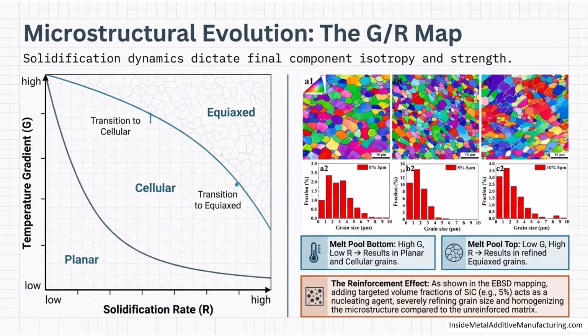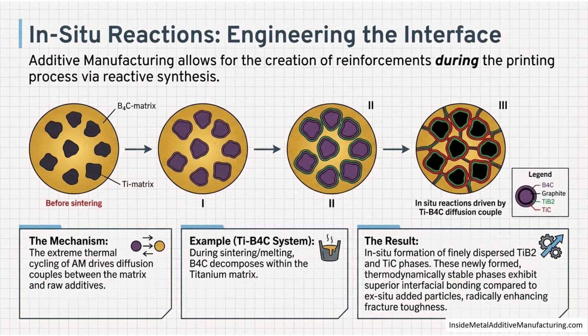Notice the reinforcement effect in the EBSD mapping. Adding targeted volume fractions of silicon carbide acts as a nucleating agent, severely refining grain size and creating a more homogeneous, equiaxed microstructure compared to unreinforced alloys. Instead of just adding particles, additive manufacturing allows for in-situ reactions. By driving diffusion couples between the matrix and raw additives, like the titanium boron carbide system, we create finely dispersed thermodynamically stable phases like titanium diboride and titanium carbide during the print. These newly formed phases exhibit superior interfacial bonding compared to ex-situ added particles, radically enhancing fracture toughness.